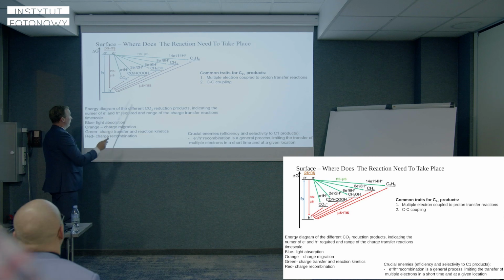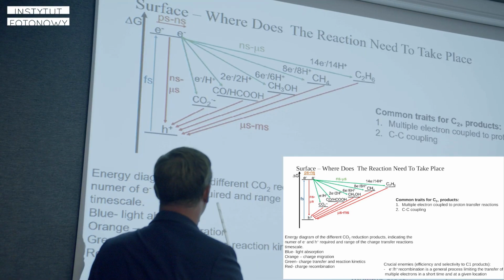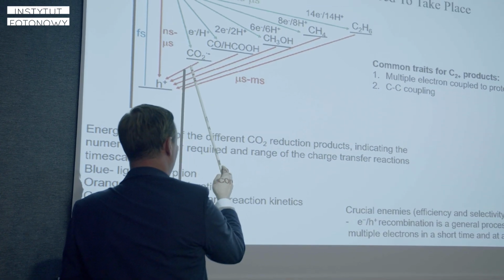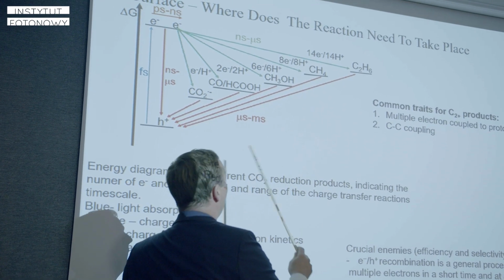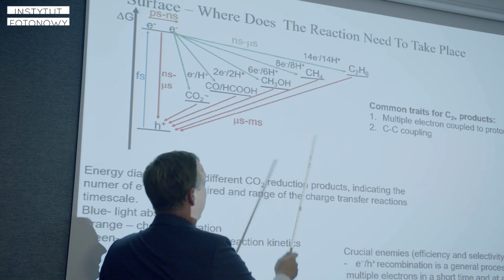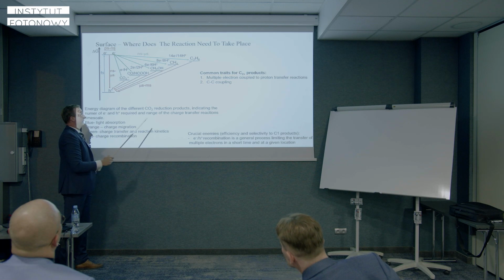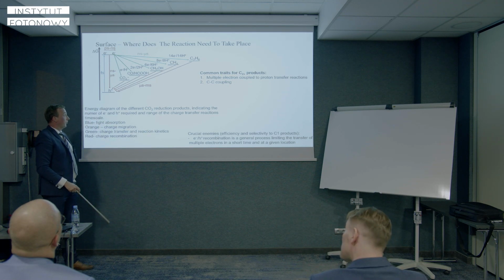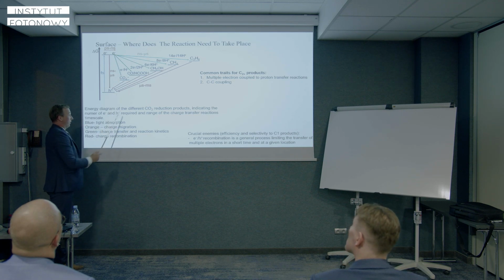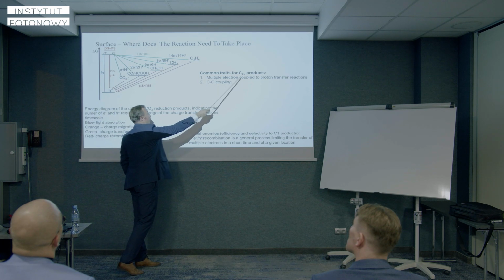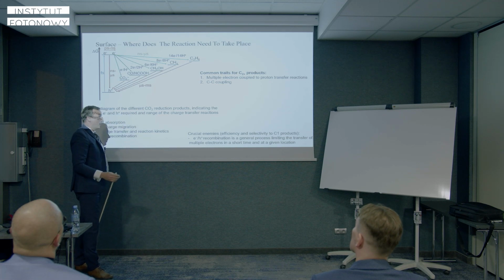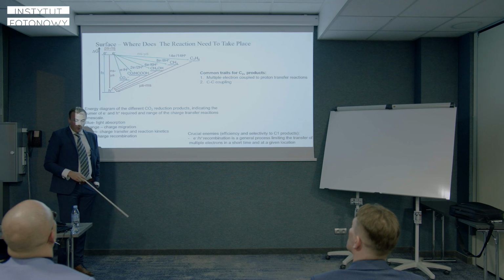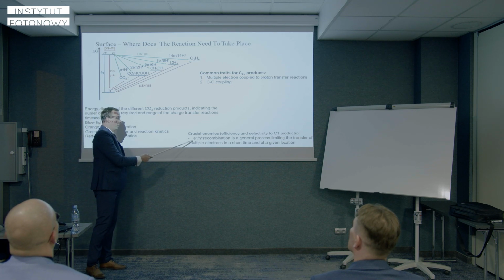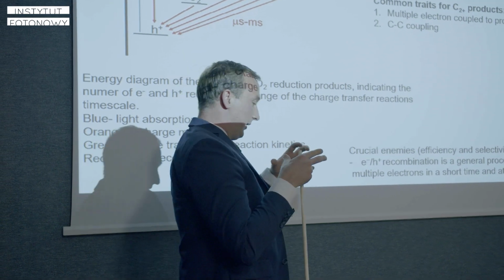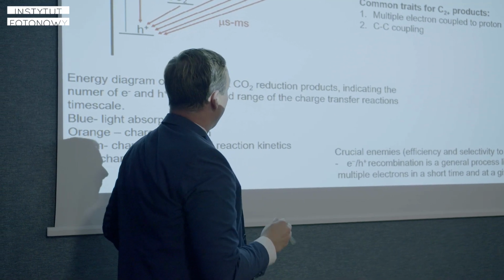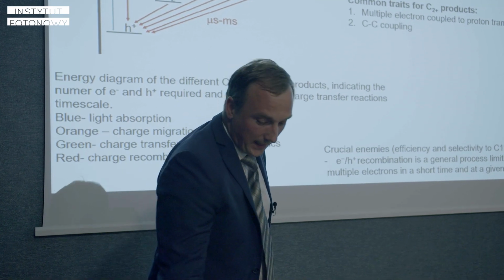When we want to create a carbon radical and we use only 1 electron or 1 hole, one carrier, it's a fast process and the time is not very important. But when we want to create C2 products or more, our system needs many more electrons, and the recombination time of electrons and holes should be much longer than in the case of the 1 electron process. So the common route for C2 products is multiple electron coupled to proton transfer reaction and C-C coupling. And our crucial enemy is electron-hole recombination, so the reduction process should happen in a short time and in the same place, the same location.